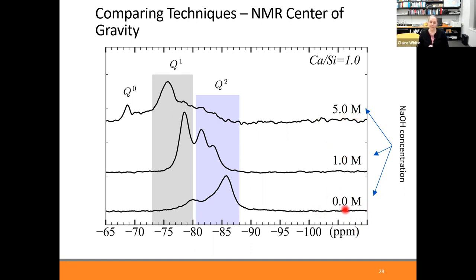So when you synthesize the gel without sodium hydroxide in there, we end up with this spectrum here, which shows that this gel mainly consists of Q2 silicate units. So silicate units tend to be bonded to 2 other silicate units, and that's reminiscent of those silica chains that I was talking about previously. Now, when the sodium content increases, what we find is that things are shifting towards the left on this screen. And so the gel is becoming more depolymerized due to the presence of sodium during synthesis of the gel.